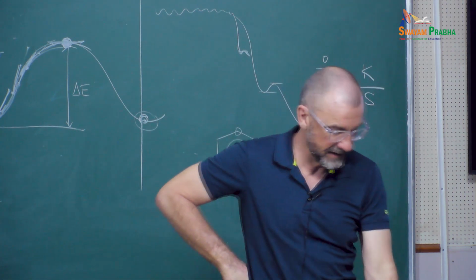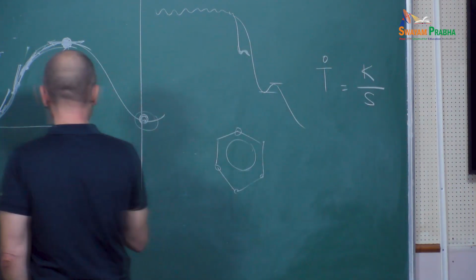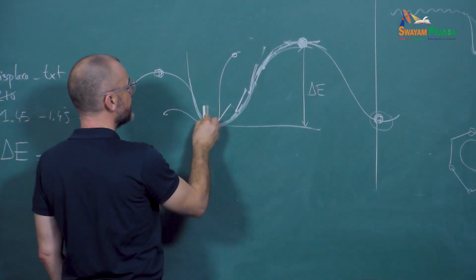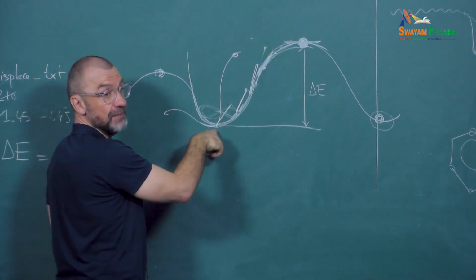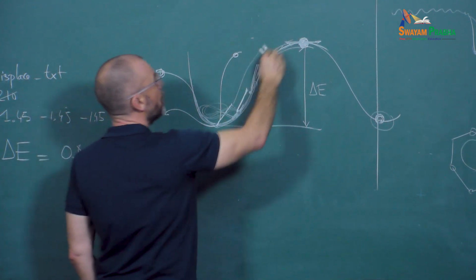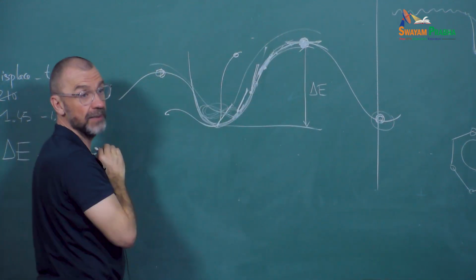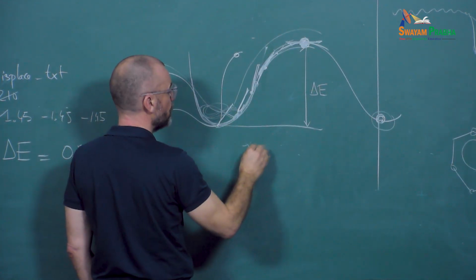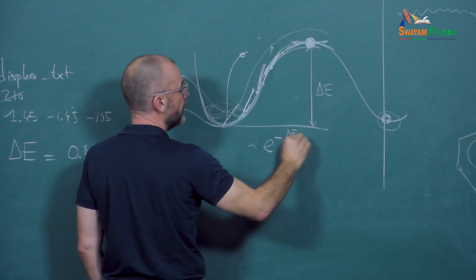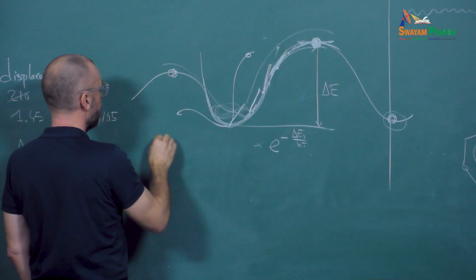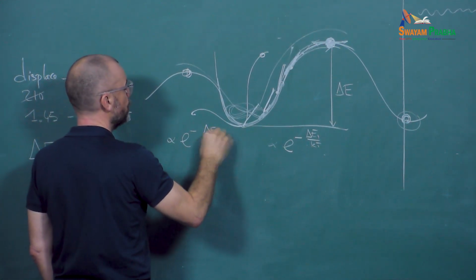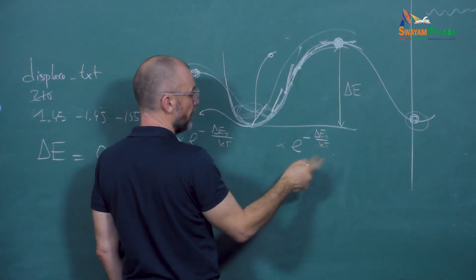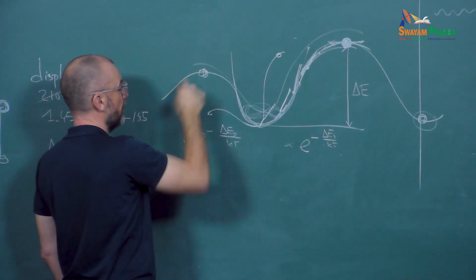So the idea is that, for example, I'm here and I have two states. I know that my system is going to vibrate around that minimum until at some point it's going to go above either that barrier or that barrier. And I know that the probability to go above this barrier will be proportional to exponential minus delta E1 over KT. And the probability to go above this one is exponential minus delta E2 over KT. And I know that the characteristic time to go above this one will be proportional to exponential plus this. The characteristic time to go above this one will be plus.